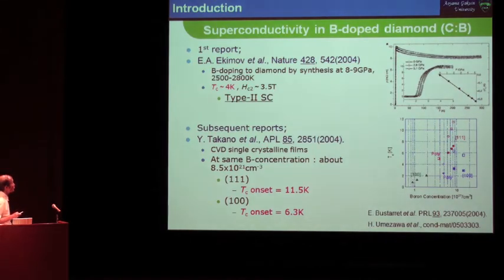Superconductivity in boron-doped diamond was reported by Ekimov, with TC about 4 Kelvin. After that, a subsequent report was made by Takano's group using a CVD single crystal film, and it is a long story. However, the conclusion is that TC on the 111 substrate is almost more than 10 Kelvin.